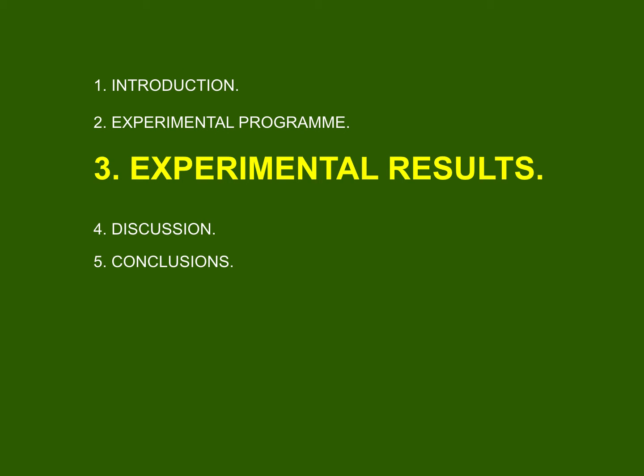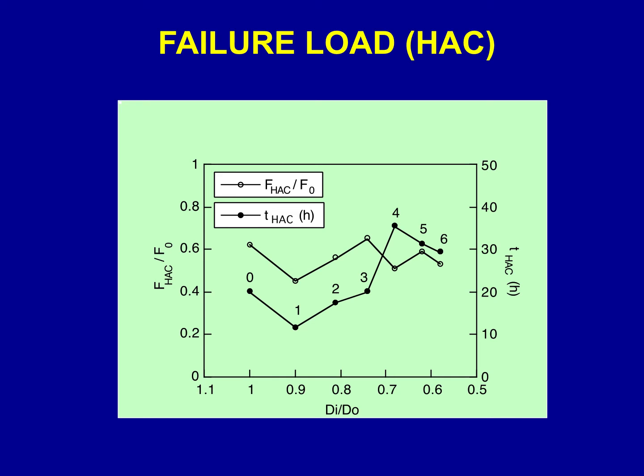Let's go to part 3, experimental results. This is a plot representing F HAC divided by F0. This is the load in a hydrogen environment, hydrogen-assisted cracking load, divided by the failure load in air. This is the vertical axis of the plot, the susceptibility to hydrogen-assisted cracking, on the left, and another vertical axis, time to failure, time to hydrogen-assisted cracking in hours. In the horizontal axis, we represent the degree of cold drawing, as the ratio of di versus d0, the ratio from any diameter after cold drawing to the initial diameter d0 before cold drawing.